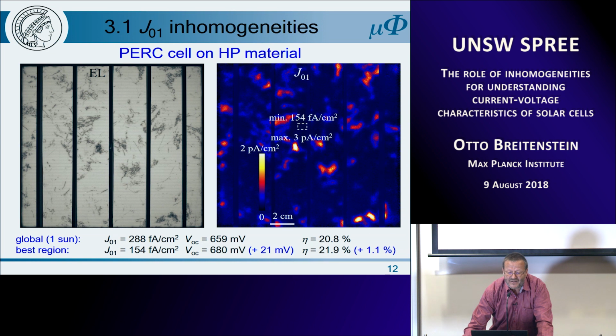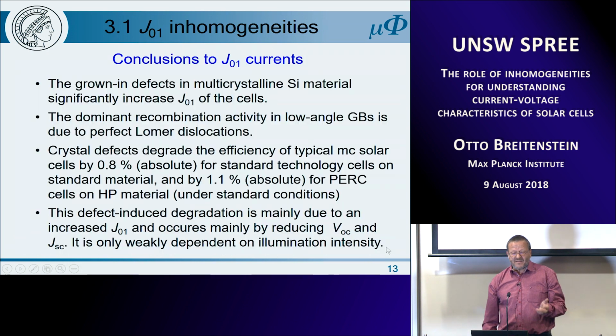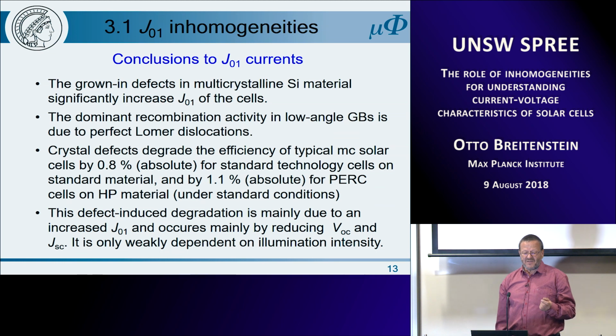And for the PERC cell, it is even stronger. On the one hand, the dark currents are lower. So the global J01 is only in the 280 femtoampere per square centimeter region, and in the best region it is as low as 154 femtoampere. So here, if we could get rid of the defects, we would win 21 millivolts and 1.1% absolute in efficiency, which leads us to the conclusion that the grown-in defects in multicrystalline silicon significantly increase J01 of the cells, which could be expected, but now we can quantify this.